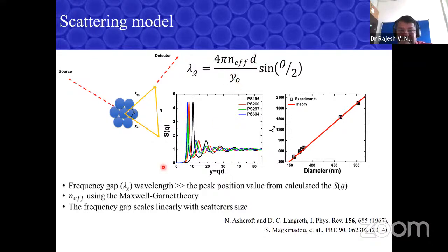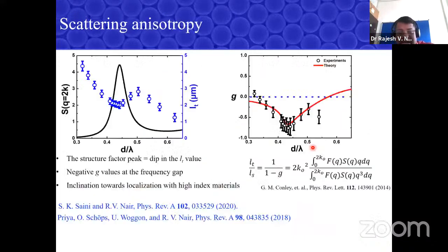a structure factor. So we calculated the structure factor for our sample, and you can see that as you increase the diameter of the scatterer, the structure factor has a large frequency shift. And you can see that if you put a y0 here and measure for different samples, this new frequency gap for short range order is actually scalable, and the symbols are experiment and the lines are the theory. So we could actually repeat for different samples, and we could predict this theoretically. Yes, you give me a sample of this diameter, I can predict where the frequency gap comes. And then we went on to do a lot of scattering estimations.